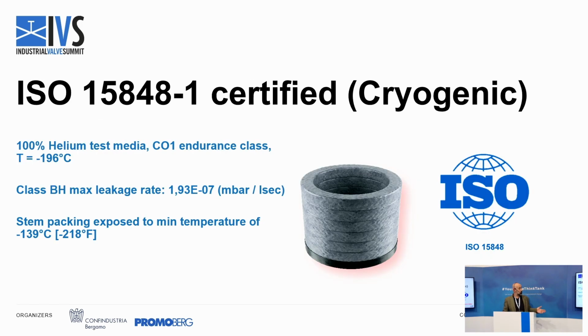So as I was saying, we used the 15848-1 test because one of the temperature classes goes down to minus 196. We tested on a valve because 15848 is a test on a valve. It's not a test for the compression packing itself. We also checked the temperature, that it was the actual temperature on the stem in that position. It was minus 139 degrees. So we are in the cryogenic state. There was no extension, so the temperature was that low because of that.